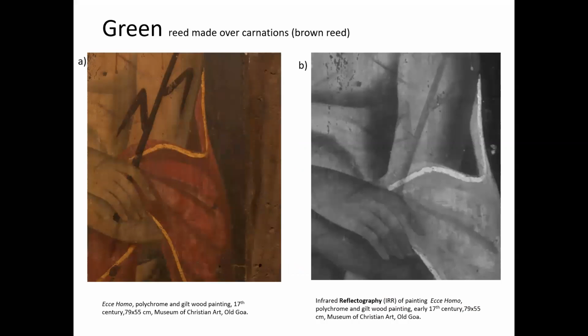In the green color, it is the most interesting color of this painting, because the results have shown that the green is made of carbon black and sericite pigments, but it has also a copper-containing pigment, probably verdigris, that is often found in Portuguese paintings of the century also. But this pigment was not possible to be identified by micro-Raman technique.